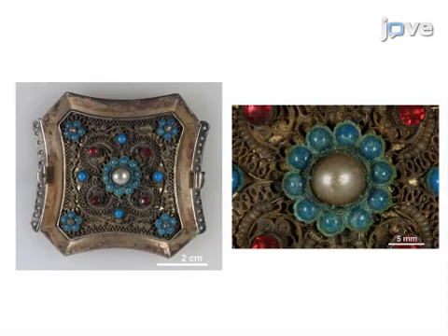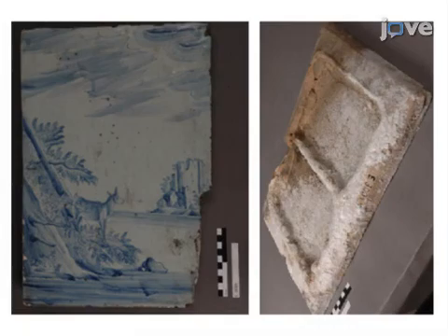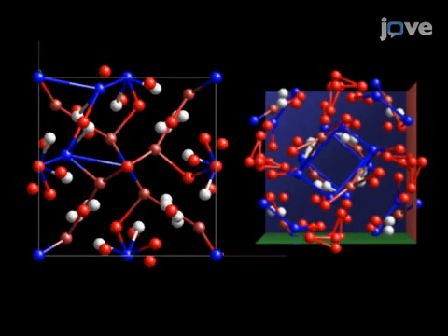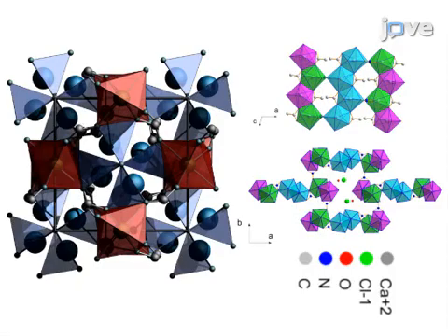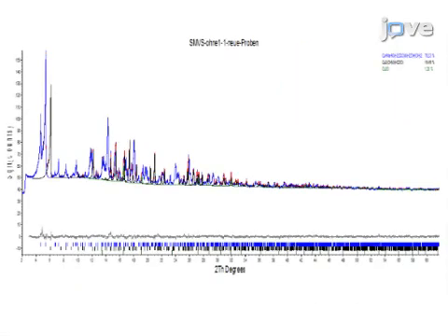High-Resolution X-Ray Powder Diffraction was used to determine the crystal structures of two long-known corrosion products on historic objects. Standard measurements using a state-of-the-art laboratory high-resolution powder diffractometer in transmission and Debye-Scherrer geometry using monochromatic X-rays were performed. Crystal structure determination of sample 1 was performed by iteratively combining reciprocal and direct space methods with difference Fourier analysis. The determination confirms the exact composition, improves our understanding of the decay mechanisms, and allows full quantitative phase analysis of corrosion products.